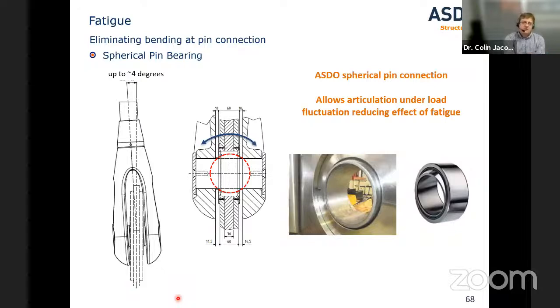Another way of eliminating some of the bending at the connection plates is by use of a spherical pin. So we can provide a spherical seating inside the pin. This allows up to say 4 degrees of rotation to occur without putting any bending into the system. Because what happens if you don't have that, often it's the bar, the weaker part in bending, that suffers, and this is where the failure will occur. So this can also alleviate fatigue issues in tie rods.